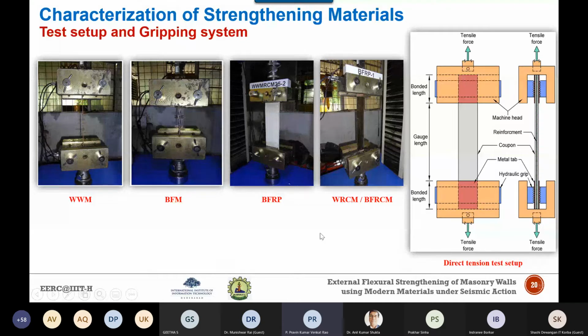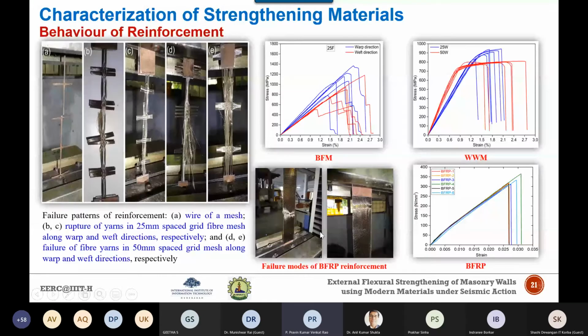Here you can see the test results of the welded wire mesh and fiber mesh. From the stress strain curves, you can see that the wire specimens of the welded wire mesh have shown a non-linear behavior, however with much lower ductility in comparison to structural steel and rebar, especially in case of the 25 wire mesh, before the wires ruptured. Now the fiber yarns of a roving have shown linear stress strain curves and a brittle failure.